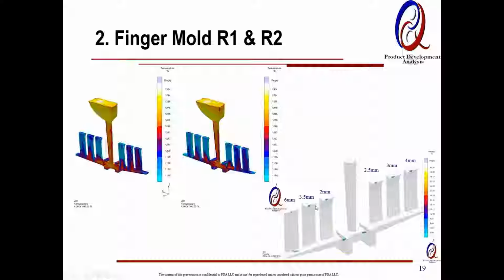So that was on spiral. Then we made finger castings. It's a typical 60-45-12, the commercial alloy, and these are the process conditions. And you can see the filling pattern quite uniform. What you see here, we had thicknesses of 2 millimeter, 2.5, 3, 3.5, 4, and 6 millimeter, all poured under the same tree. And we just wanted to see, this is quite common, that in any industrial casting you may have a combination of all these thicknesses, and we want to make sure in the high stress area it predicts the properties and the soundness that the mechanical engineer wanted to have from FEA and fatigue calculation.